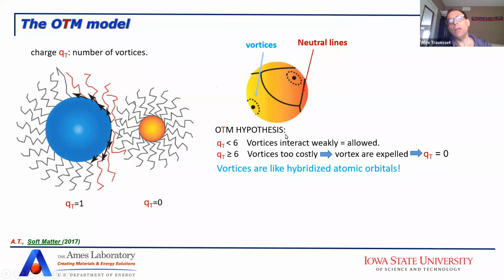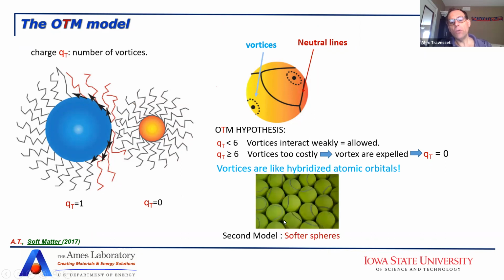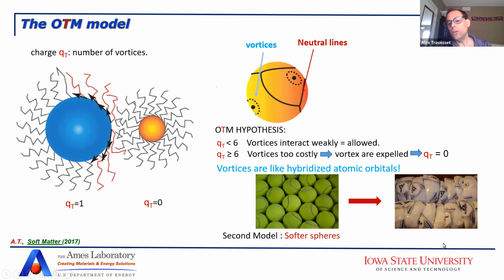And in that particular case, you have to have a situation where there are no vortices, and this is when the nanoparticles behave as hard spheres. So basically what we have here is a situation where we go from softer spheres to a situation where, in certain conditions, they can undergo large deformations. But these large deformations are not arbitrary. They are determined by these vortices, and we can exactly compute what will be the packing fraction.